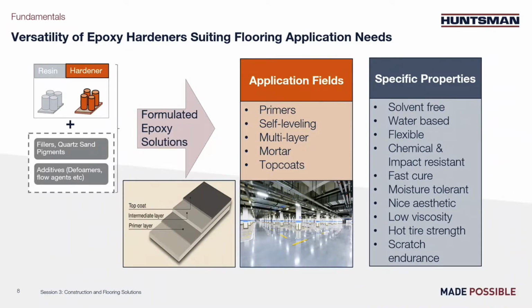For instance, a waterborne solution requires specific choice of components. Also, when good surface appearance is needed under tough conditions like low temperature and high humidity, a specific hardener should be used. It is generally the hardener which is key to the final properties, whether they are appearance, kinetics, or chemical resistance.